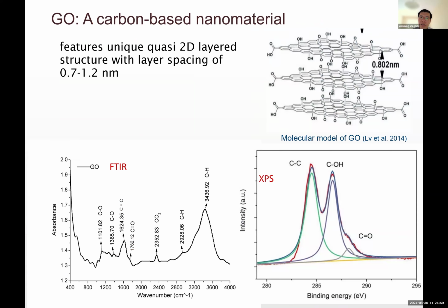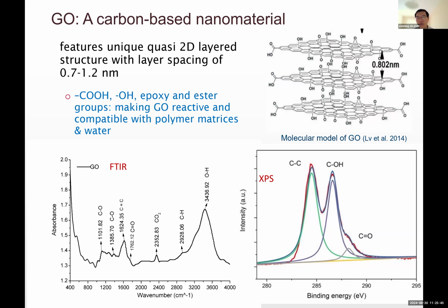So graphene oxide is a carbon-based nanomaterial. I'm sure some of you have heard about graphene, which won the Nobel Prize about two decades ago. Graphene is made from graphite, usually through either a physical approach or a chemical approach. The chemical approach we took is known as the modified Hummers' method. Basically, you use strong acids to exfoliate the nanoplatelets out of this graphite material. In the process, because of the strong oxidation, the nanoplatelet surface would have functional groups, such as hydroxyls and carboxyls, as revealed by the FTIR on the left and the XPS on the right. So you get these functional groups, which are very beneficial because they make the graphene oxide reactive.